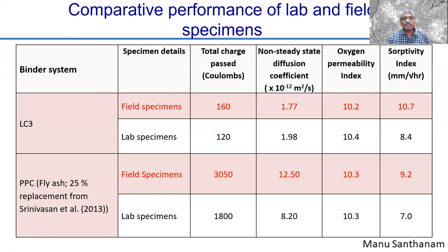So let's see how these fared. So for LC3, the field specimens, that means the specimens taken from the cores that were taken from the slab, were compared with lab specimens. These were specimens that were cured in standard conditions in the laboratory. You see, there's not much difference. As far as RCPT is concerned, you still have this 160, 120. Migration coefficient is still less than 2 in both cases. Oxygen permeability is similar. Sorptivity may be a little bit different, but more or less you get the same durability, irrespective of whether you cure it in the lab or in the field.